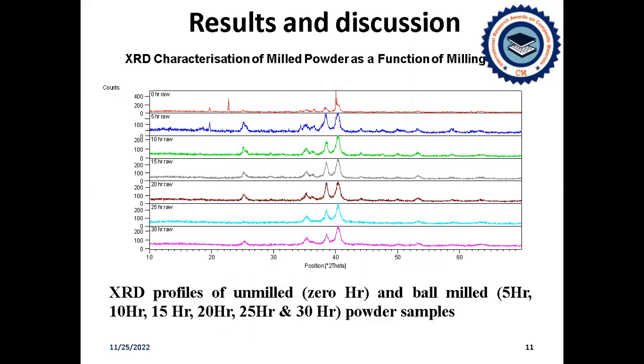When it comes to the results and discussion, this is the XRD characterization of the milled powder as a function of milling time. This graph shows XRD profiles of ball milled powder at different hours of time, that is 5 hour, 10 hour, 15 hour, 20 hour, 25 hour, and 30 hour. At each interval of 5 hours, a small quantity of powder is taken out from the jar for characterization purpose, and the XRD characterization shows the peak broadening for every 5 hours.